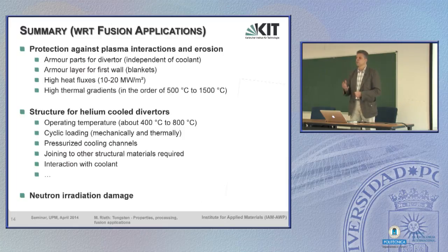We have one application to protect substructures where tungsten more or less is eroded away by the interaction with plasma and incidental particles. It's used in divertors, but also to shield the whole surface inside the fusion reactor. And here we have high heat fluxes and also high thermal gradients. Then there is a structural application for helium-cooled divertors where the operating temperature is lower. Cyclic loading has to be taken into account. We have pressurized cooling channels. Many things have to be joined, and the interaction with the coolant might be important. But also neutron irradiation damage. We will come to that later.